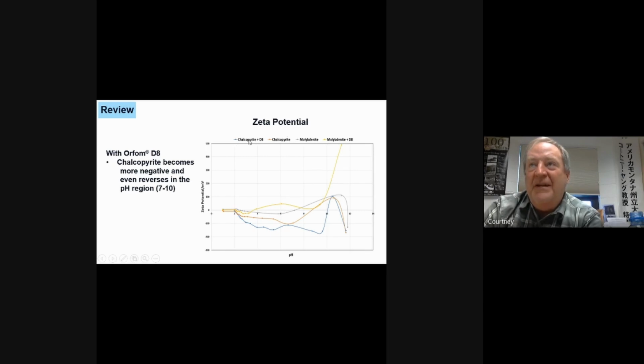And then when you add xanthate, that's this plot, right? I hate these colors. That's this plot here. And for the most part in here, you're not seeing a lot of change. You do see a fair amount of change above pH 10. We're not interested in this. We're interested in here. And of course, where you're seeing the most change is right in here.